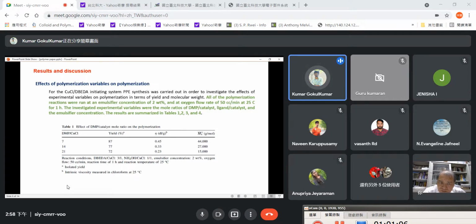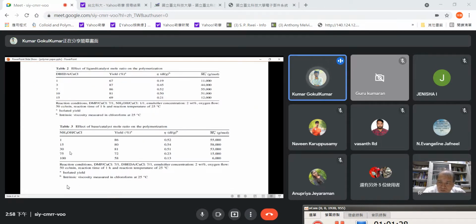The molar ratio was varied in the range of 7:1 to 21:1. As the catalyst concentration increased, both the molecular weight and the PPE yield also increased. In Table 2, a copper compound combined with an amino ligand was used as the catalyst system for the synthesis of PPE. The effect of ligands like DBEDA and N,N-dimethylethylenediamine was evaluated, with results in this table and Figure 2.